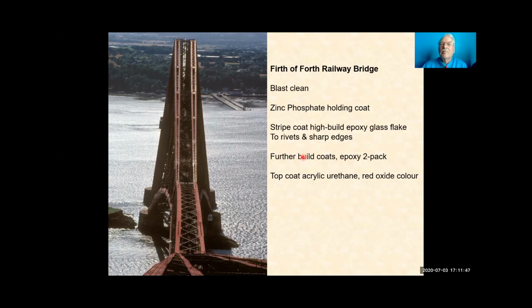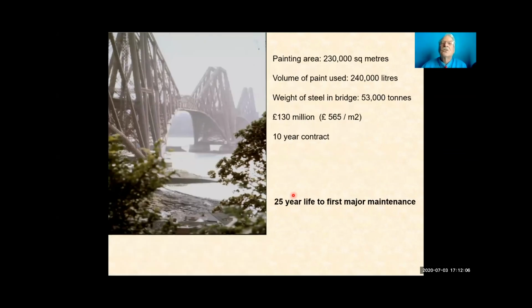So we're building up a huge dry film thickness at this stage now with the epoxies, but remember the epoxies are not UV stable. So we now have to finish off with a top coat of acrylic urethane, finish colour as red oxide. And there it is, this vast bridge, 230,000 square meters of it.